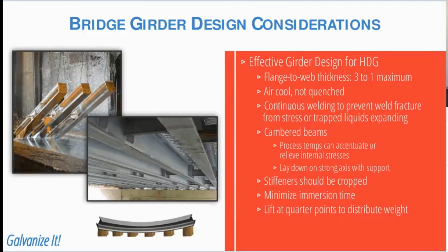Stiffeners should be generously cropped in order to allow good venting and drainage of the part, and the galvanizer should try to minimize the immersion time overall. And then any lifting points should be placed at quarter lengths in order to avoid any sort of permanent deflection or bowing from the lifting process.